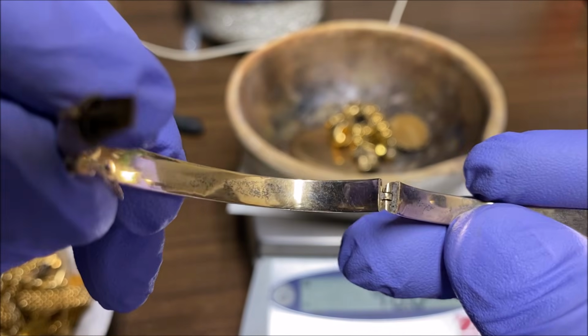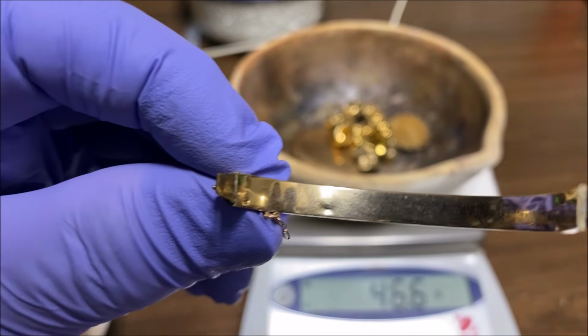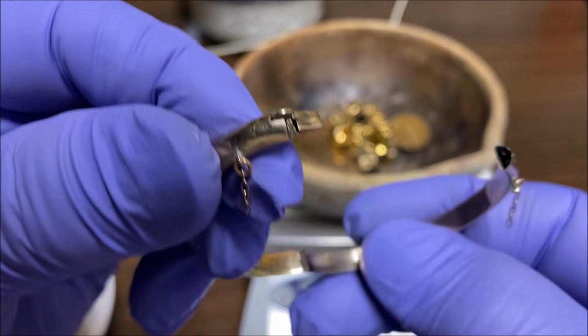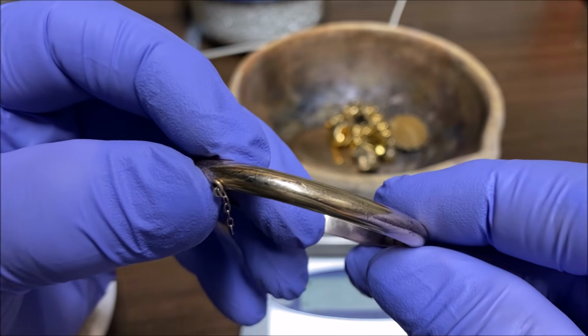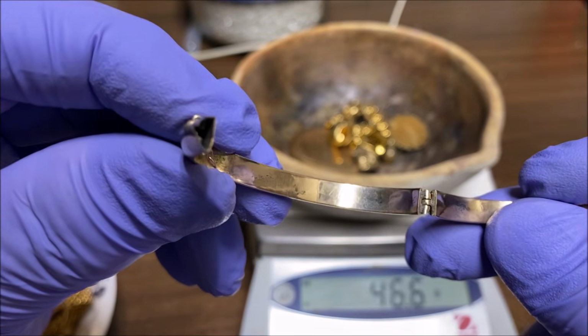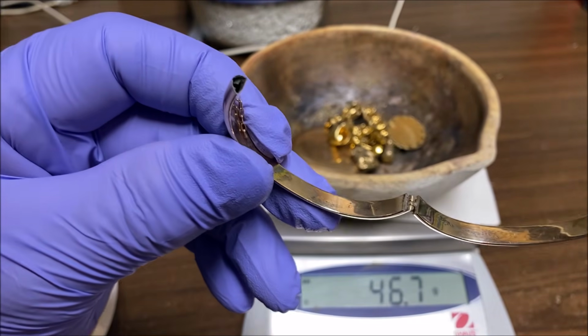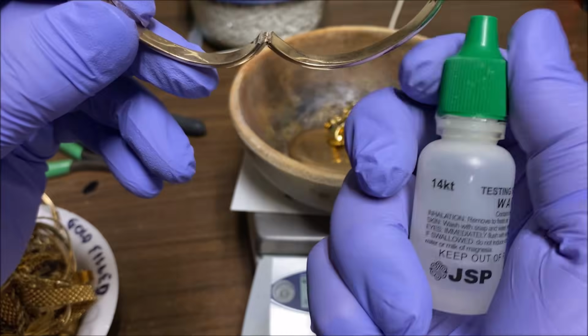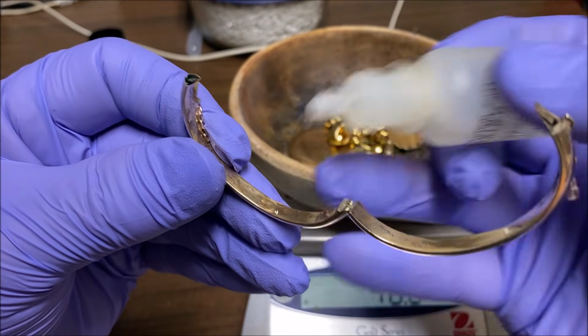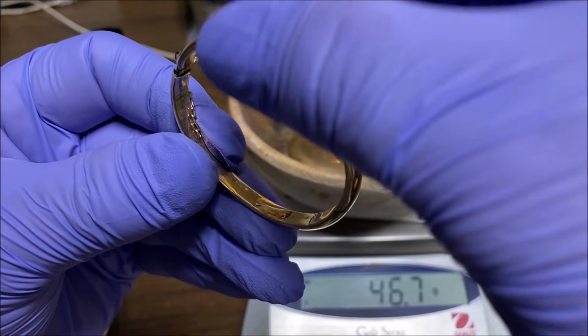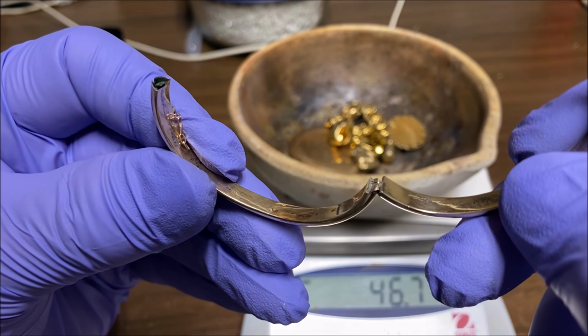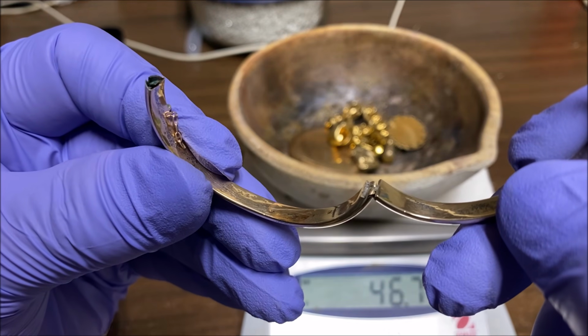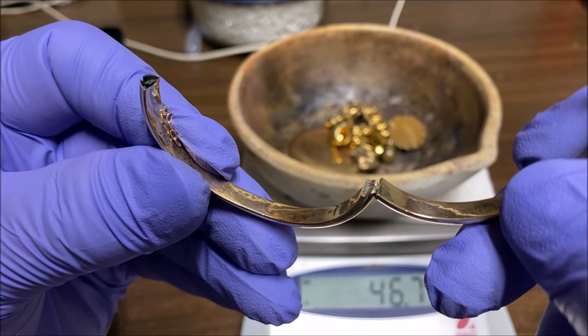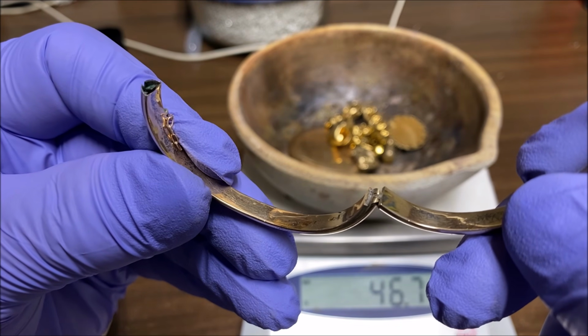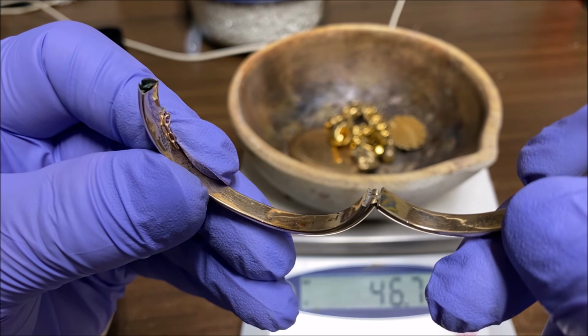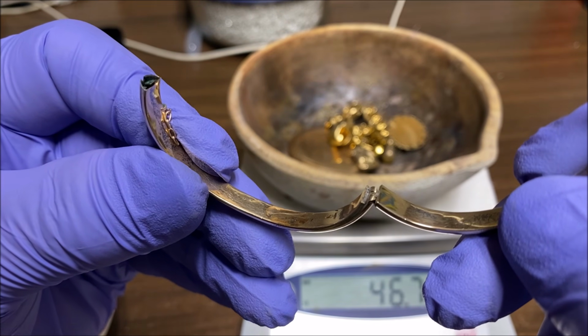Here's another piece. I couldn't find any markings on it. And so the way to test pieces that don't have markings is to just take a little bit of the 14K testing acid like this. And if it just sits there and does nothing, it doesn't bubble, it doesn't turn green, and it doesn't start to stink real bad, then chances are high that you have a piece of gold-filled material, because gold-filled material is a thick coating of karat gold over brass.